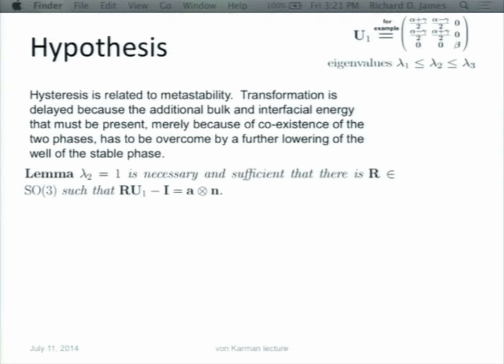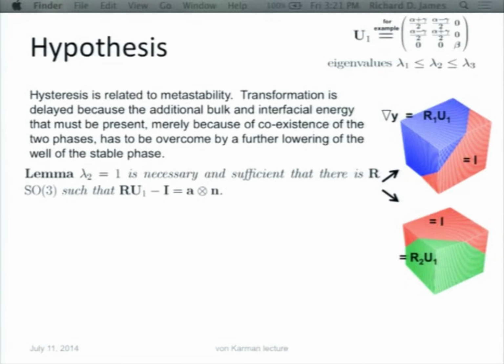But then you can also notice that, in fact, the middle eigenvalue of this matrix being 1 is necessary and sufficient that RU1 minus identity is A tensor N. That's the compatibility condition between one variant of martensite and the austenite phase. So if the middle eigenvalue of this matrix happened to be 1, you wouldn't need that transition layer. You wouldn't need those bands. You could have a perfect interface between the austenite and martensite, okay?